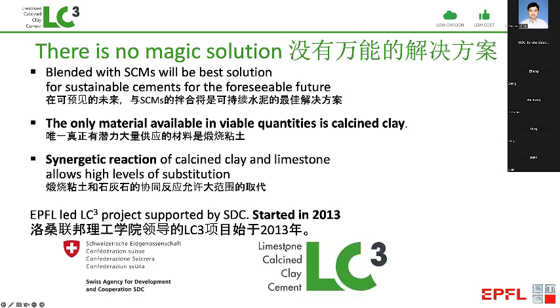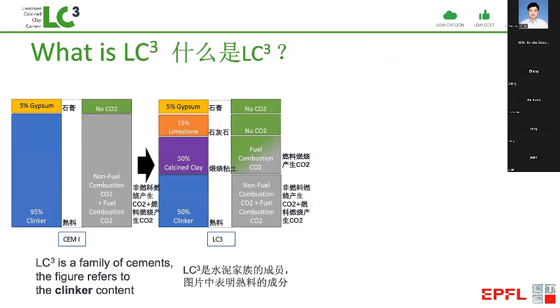And LC3 simply identifies what are the ingredients we have in this cement. It stands for limestone calcined clay cement. So why does this have lower CO2 emissions? Well, in conventional Portland cement, we have about 95% clinker, which is emitting the CO2. In LC3, we have only 50% clinker. And in fact, we can go to even lower amounts in the long term. We have 30% calcined clay, which has a little bit of CO2 from the calcination process, but this is much, much lower than for clinker. And limestone has virtually no CO2, only a very small energy for grinding is needed.